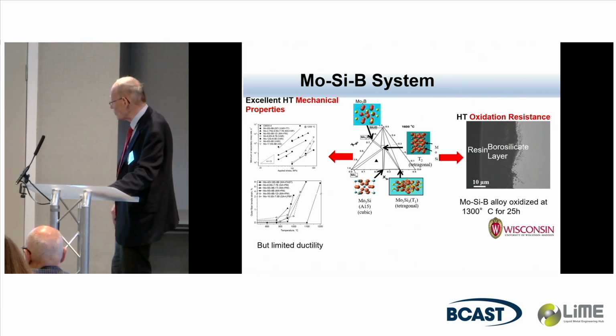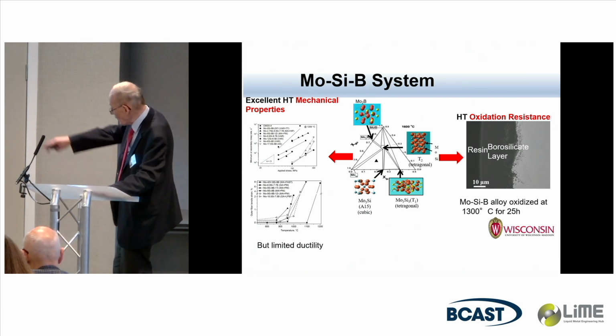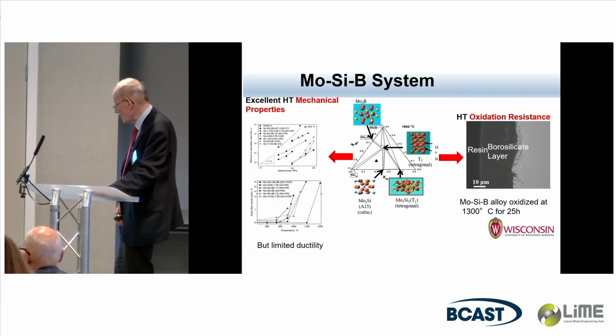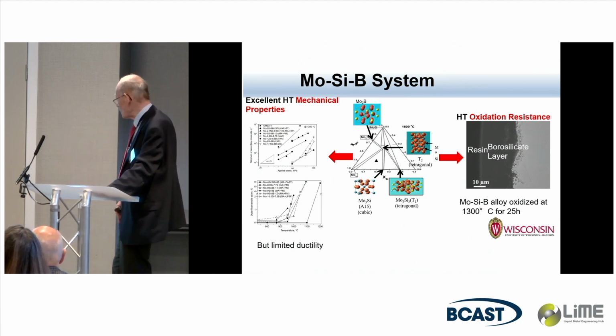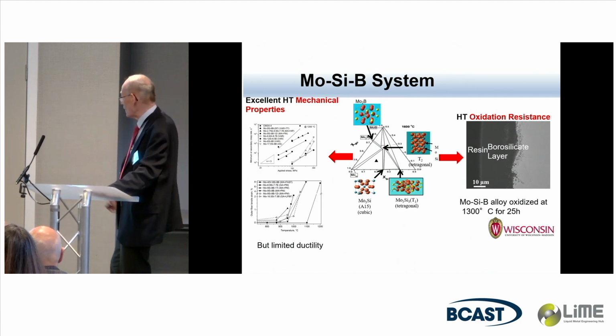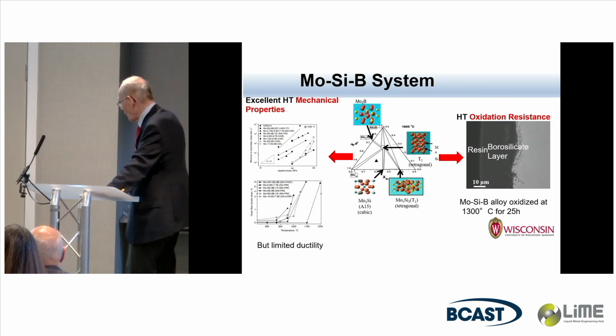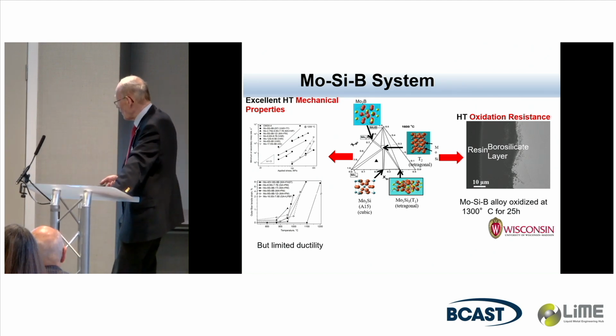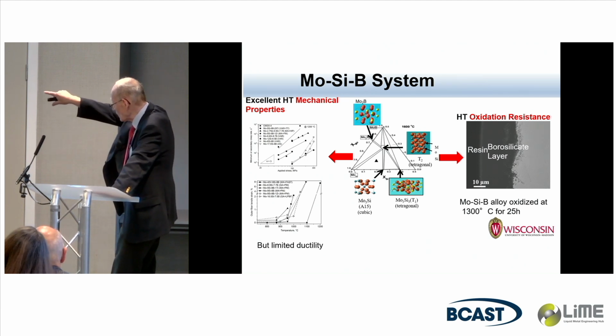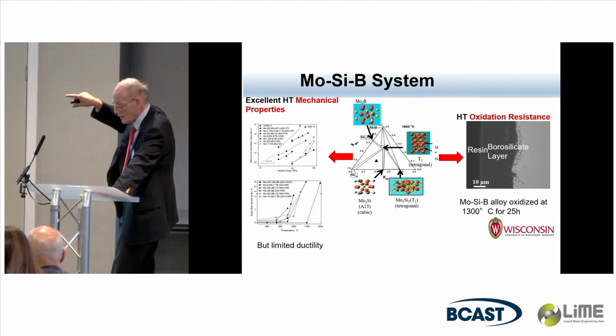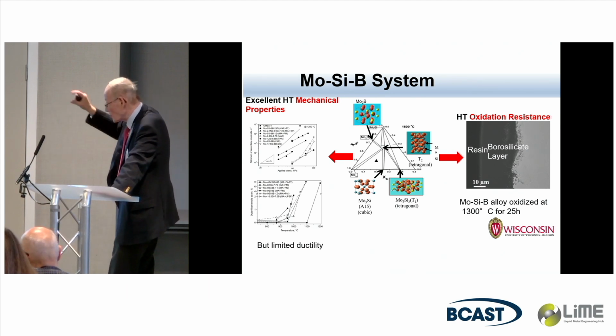So these alloys have excellent high temperature properties compared to the latest generation of nickel-based superalloys. These are orders of magnitude lower in creep rate. However, they have limited ductility and undergo a ductile-brittle transition. Their oxidation resistance is good, but not great enough. The recession rate is a little bit too high. So these are issues that have to be solved. And I want to point out that the T2 phase, this ternary intermetallic, is not a line compound. It has a width to it, a homogeneity range.